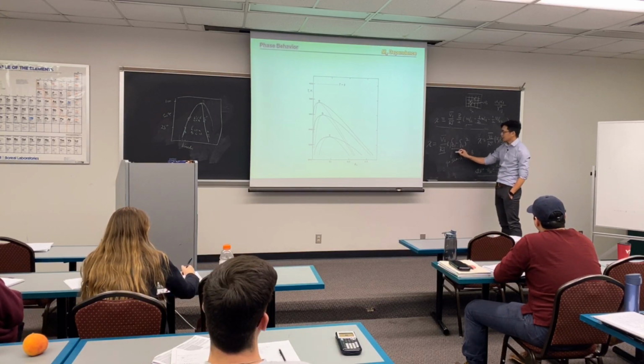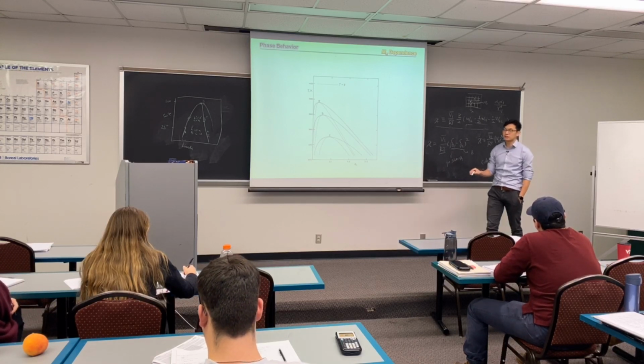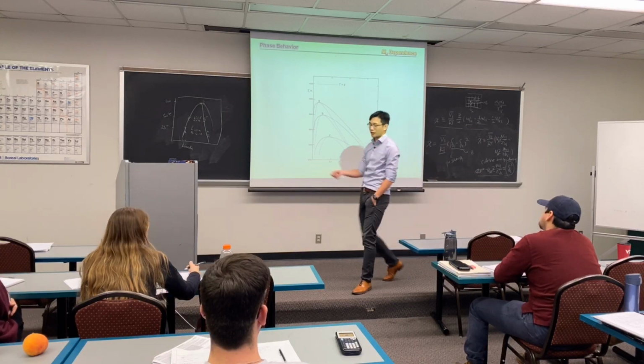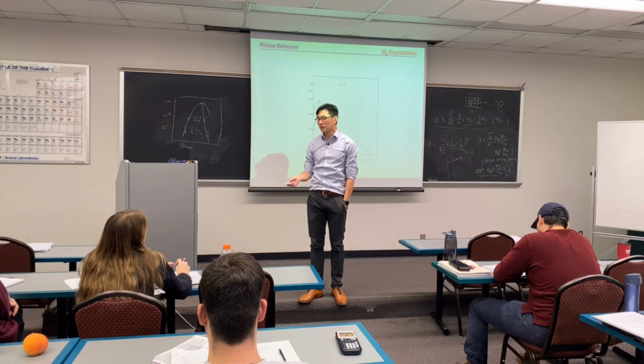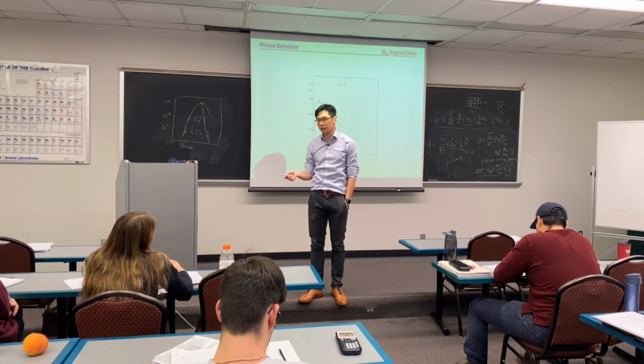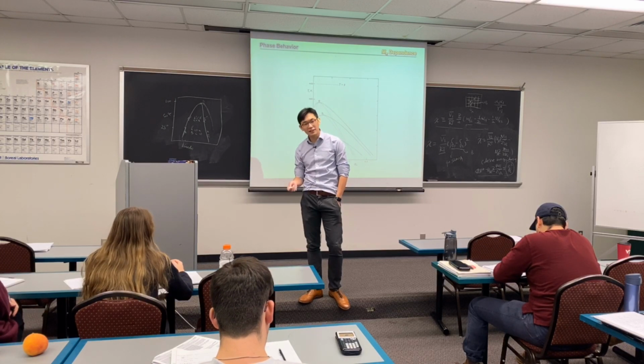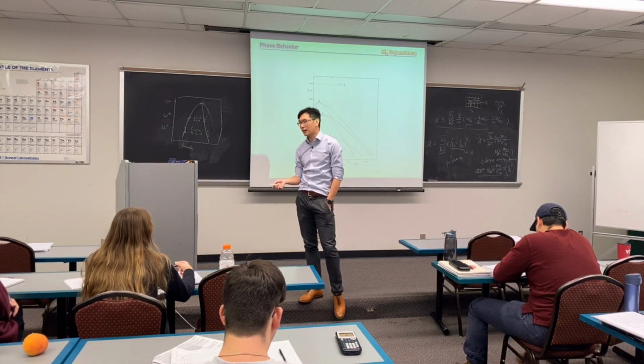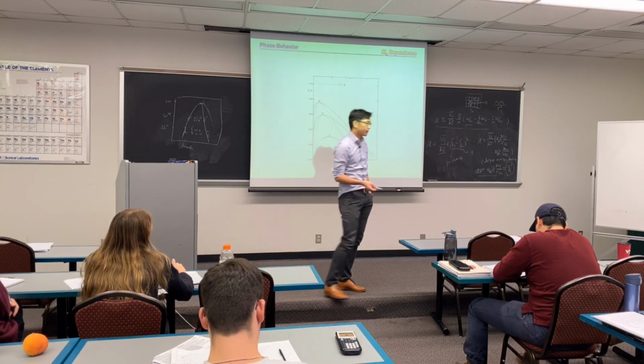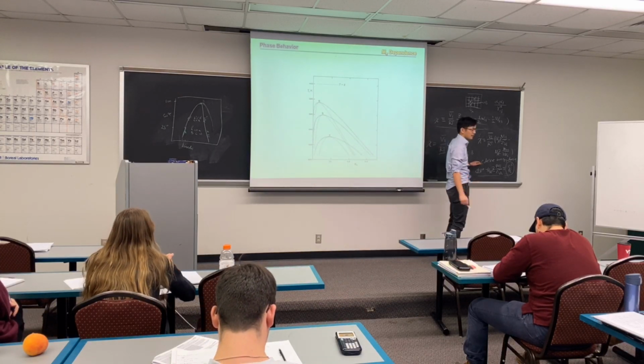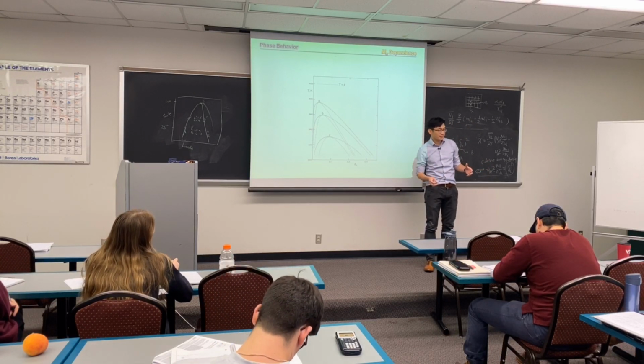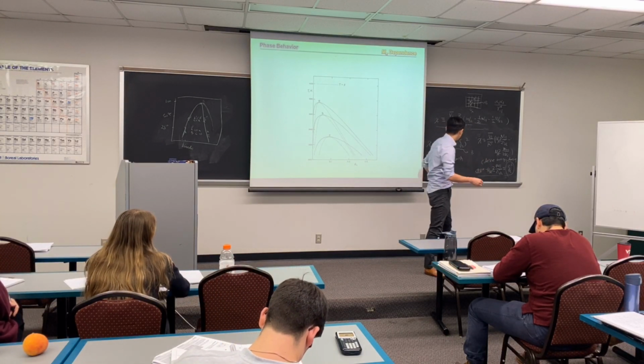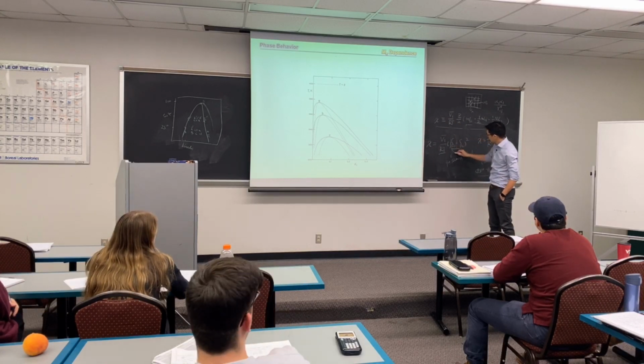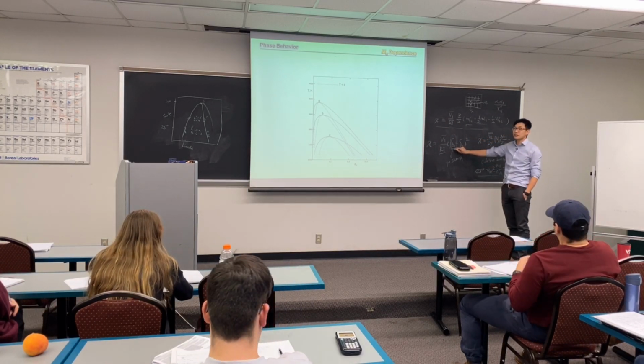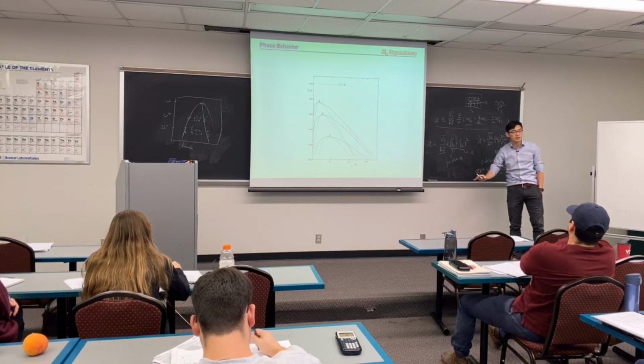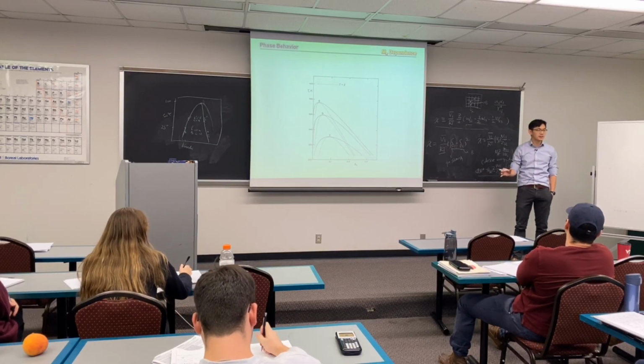To be more exact, chi cannot describe one material. If you have only polystyrene, you cannot state a chi for polystyrene, because chi is related to the interaction parameter with a second molecule. Let's say you have toluene and hexane. How can we get the chi for these two? Well, cohesive energy gives you a simple way to get the chi value. You can look up cohesive energy. Cohesive energy doesn't depend on two molecules. It is only determined by itself.